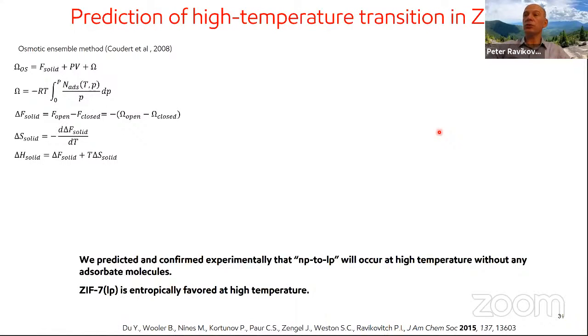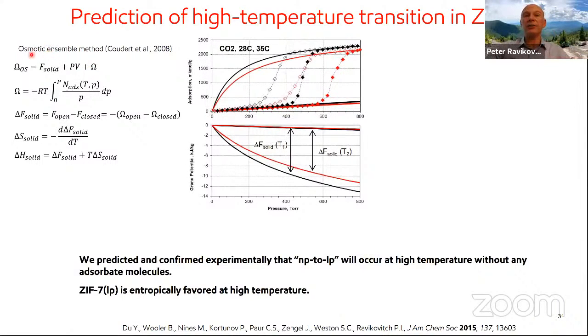You can try to rationalize what's going on by using the so-called osmotic ensemble method pioneered by Coudert and co-workers. If you look at the osmotic thermodynamic potential of the system, which includes the free energy of the solid, a pressure term, and the grand potential related to adsorbed molecules. In this case, by applying the osmotic ensemble method, you can look at the adsorption isotherms on the materials which exhibit steps like this and fit adsorption in individual structures, like a narrow pore structure or large pore structure, and you can calculate the free energy difference between, say, the large pore and narrow pore structures.